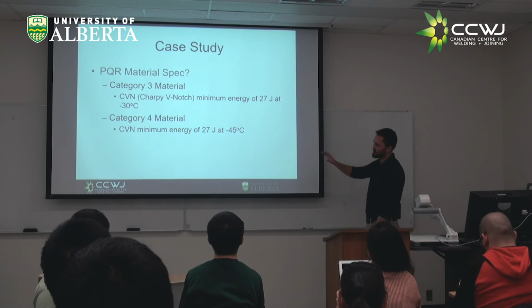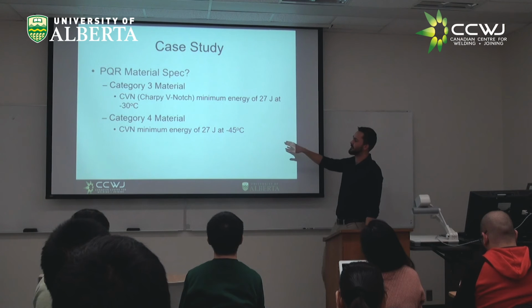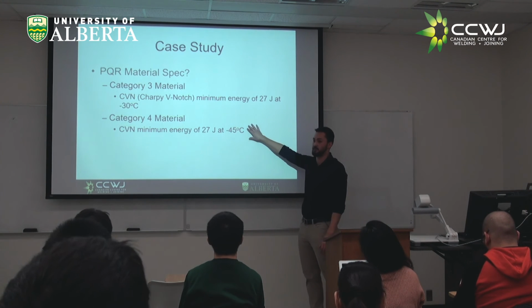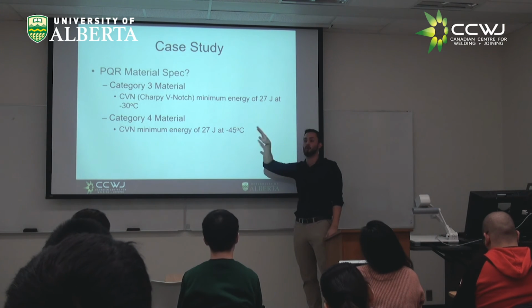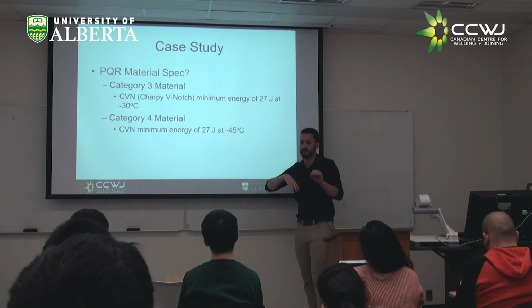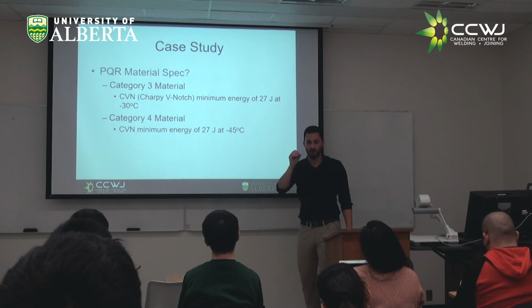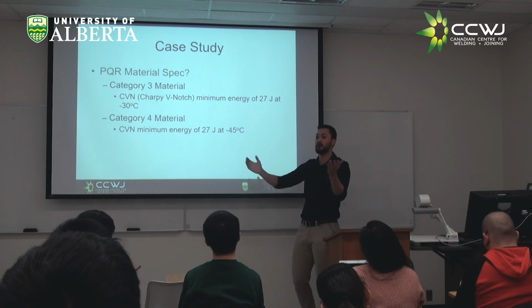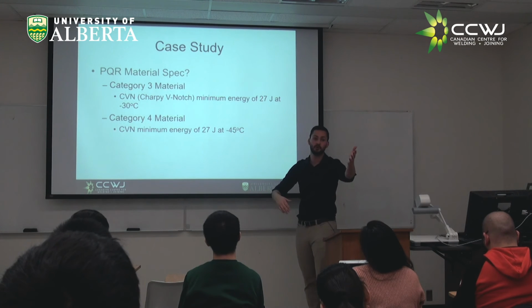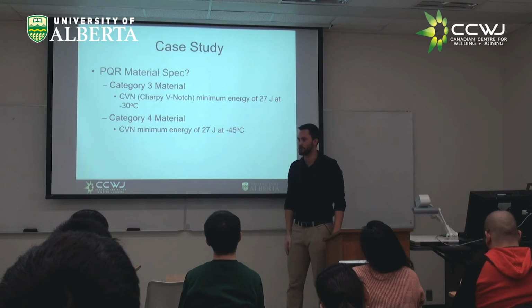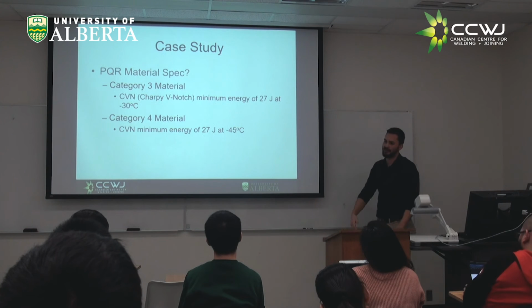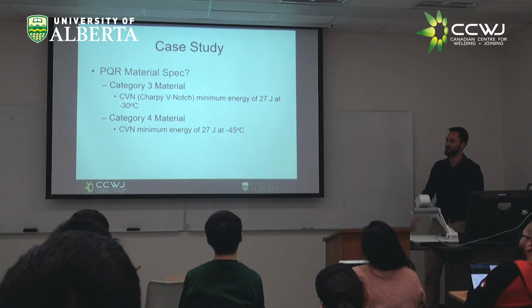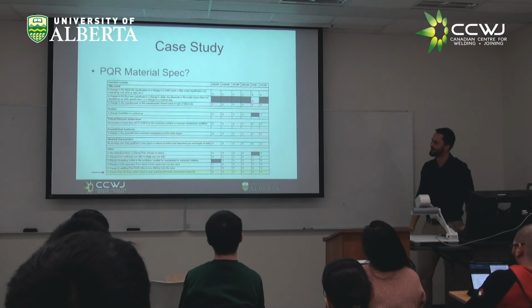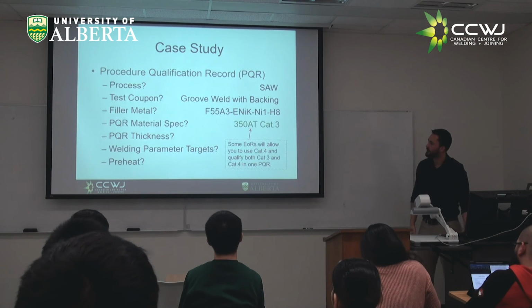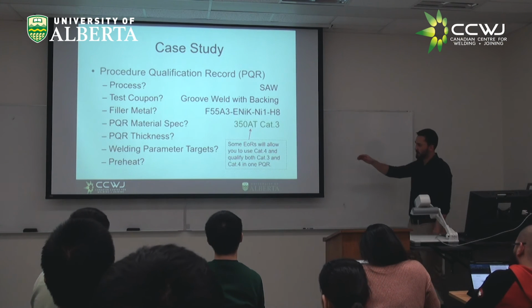And what's even stupider, this is a little thing that's been a personal annoyance of mine the last little bit, is that if you test a Cat 4 material, and you go back and you test a Cat 1 material, so that's passing 27 joules at 0 degrees C, now you get all of them. Now you've proved you can do it at a high temperature, and you prove you can do it at a low temperature. For whatever sense that makes, that's the way that they do it, but it's completely a money grab in my opinion. I'm bitter about it. So we have our material picked out.